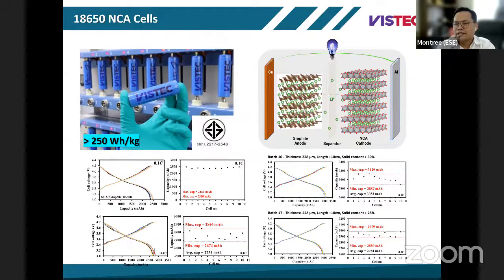That is one thing. And the second thing about our technology is the additive in the electrolyte. We add a new electrolyte that can make the passivation layer at the graphite, or in our field we call it SEI, to make it more stable. And actually we make it like an insulator coating. When we have an impact, once we abuse the battery by mechanical energies, the contact between anode and cathode happens, but it does not allow a short circuit. So we achieve safety. That is another thing from the additive.